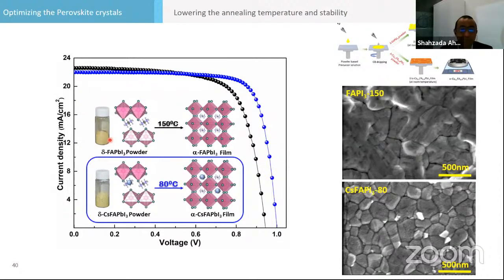This is a perovskite powder. We are able to directly synthesize the powder. The yield is also very high. And believe me, this small bottle is sufficient to make half a kilowatt of solar cells. And also we were able to make it at a very low temperature, only 80 degrees centigrade. Normal FAPbI3 powder is about 150. When we alloy with cesium, we can make it at 80 degrees centigrade, and it works.